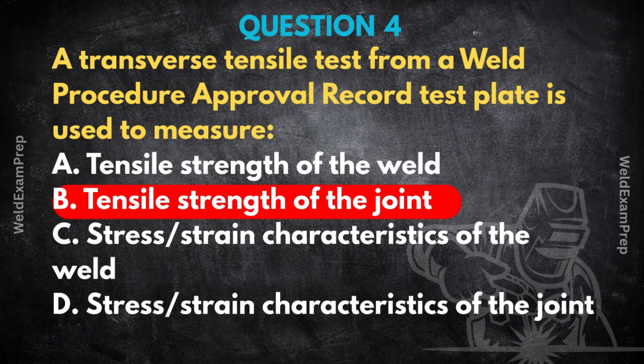So when you prepare that specimen and pull it in a tensile testing machine, the piece being tested includes not just the weld metal in the middle, but also bits of the heat-affected zone, the HAZ, on both sides, and some of the original parent or base material on either side of that. So it's got everything in there. It's got the whole system right across the connection. Therefore, the test isn't just measuring the strength of the filler metal that was deposited. Instead, it measures the overall tensile strength of the entire welded joint. It's basically designed to find the weakest link across that whole transition: weld, HAZ, parent metal.